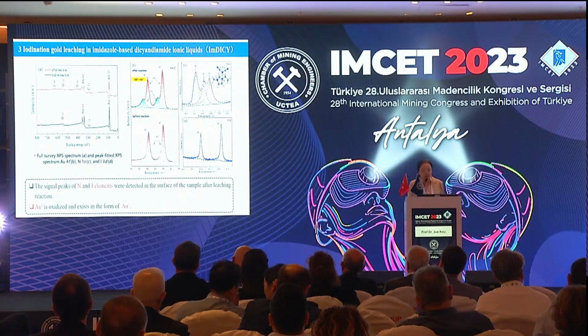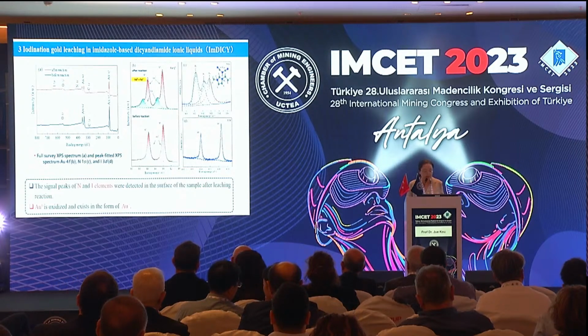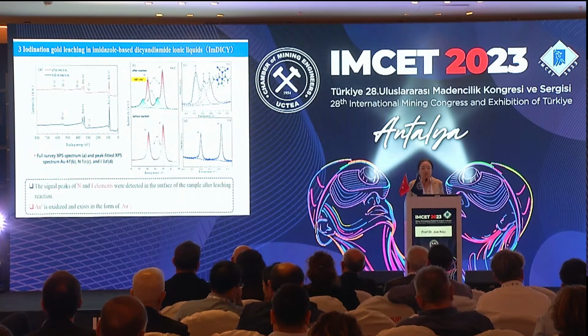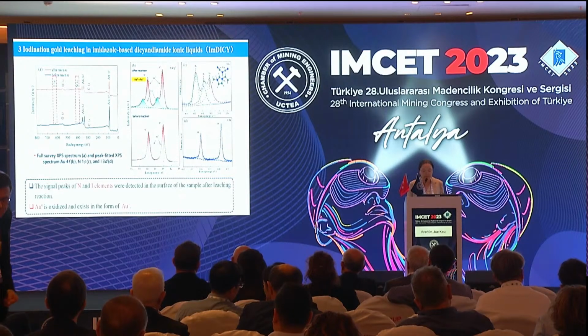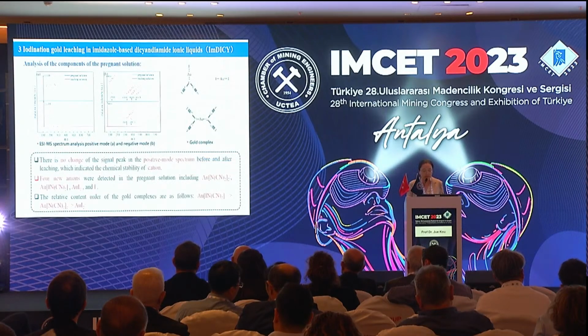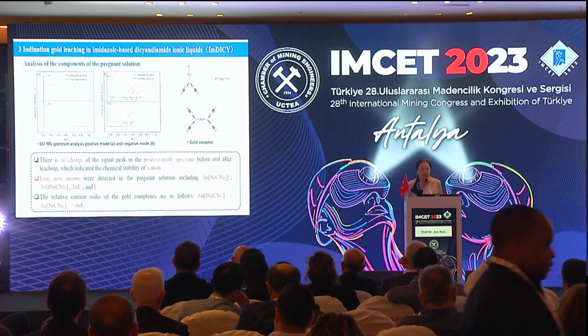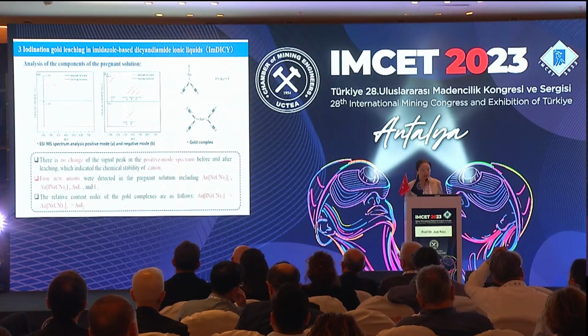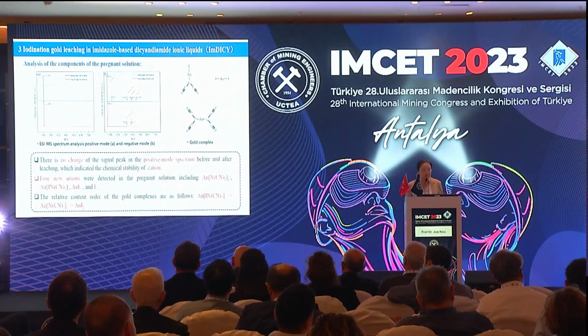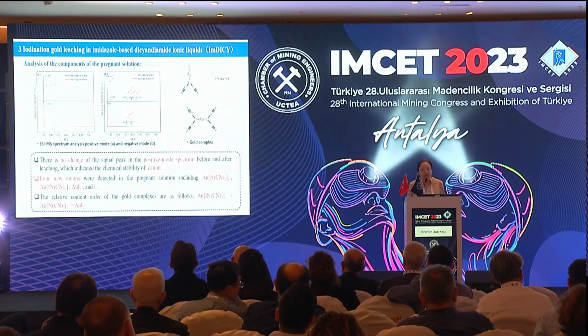And in the leaching residue, we find the nitrogen and iodine elements on the surface. The gold is oxidized in this whole process into gold(I). And this is a very interesting result. We use the ESI-MS spectrum to test the pregnant solution. We can see that before and after leaching, the cations in this pregnant solution have no change, which means the imidazolium doesn't change at all in the whole process. We can reuse it and recycle it in our process.